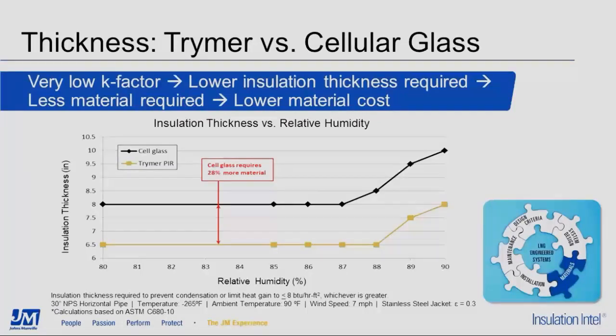Below that relative humidity level, the design criteria of limiting the heat gain dominates. But at all levels of relative humidity, the thickness required for cellular glass is 1.5 to 2 inches greater than that of PIR. Converting this thickness into an amount of material required, the cell glass would require about 28% more material than would an insulation system based on PIR.